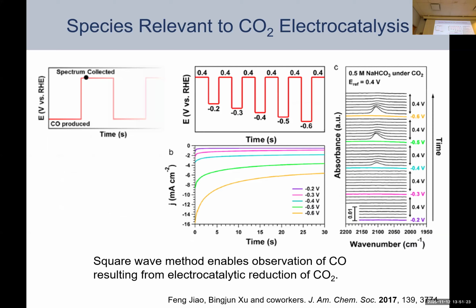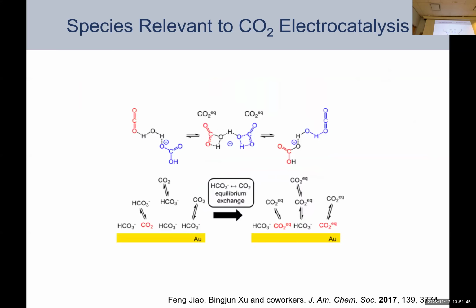So you can see an example of this here where we don't need to be applying just a fixed potential, but rather you can jump back and forth. So this negative applied potential is where they generate the CO and then measure at 0.4. And now you can see these really beautiful ATR-SEIRAS spectra. So having employed this clever pulse trick, they were able to study, it's a long story, but a really good one, so I recommend this paper if you're interested. There's a whole host of isotopic labeling experiments and mass spectrometry coupled with ATR-SEIRAS experiments to look at spectroscopy of the interface. And really this is pointing at the fact that there's a really fast equilibrium exchange between bicarbonate and CO2, where the soluble bicarbonate acts as a local source of CO2 that can be reduced at this interface.